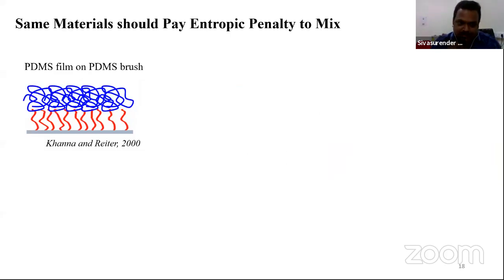So to do that, what Khanna and Reiter in 2000 have done, and what I have been doing also, is that they have created a PDMS brush. You can create this with PDMS or polystyrene or polymethyl methacrylate; that is up to what kind of system you look at. But they have chosen PDMS, polydimethylsiloxane, as a model system, and they have created a very dense brush here, which is given by these red chains.